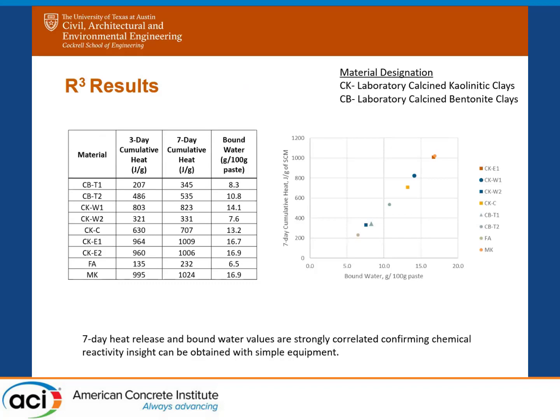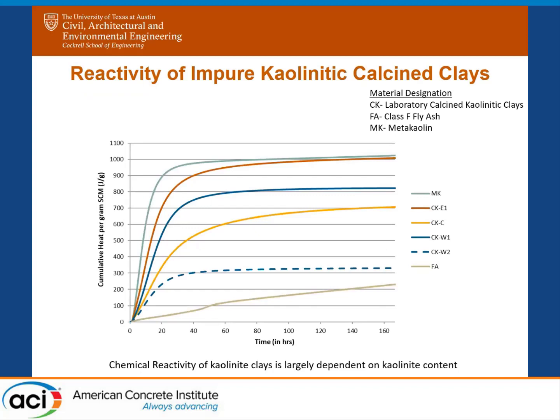So these are your typical results from this test, doing both components. The bound water is really just to gain chemical reactivity insight with simple equipment. You can see on the right that these two values, the 7-day cumulative heats and the bound water, are pretty well linearly correlated. So that would say that with this test, you can use either or. And you can see that fly ash is at the bottom, and the commercial metakaolin is at the highest chemical reactivity, which is expected. So from here on out, it'll just be about the isothermal calorimetry, not the bound water.